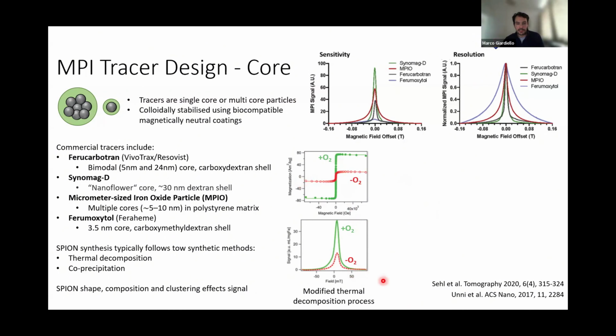So this is a thermal decomposition particle. They're varying the oxidation of the particle, and you can see how strongly it magnetizes, and how quickly. On this particular one, made using thermal decomposition, when they add oxygen and completely make their core a single crystal, a single type of core, you get this very strong magnetic signal and very quick response. And this is the signal intensity, which is just the derivative of that sweep. So that's turning that into these point spread functions.